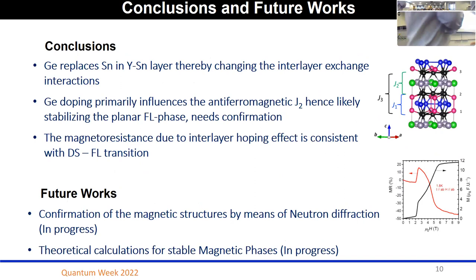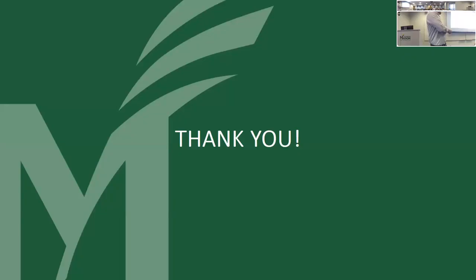So another reason to believe is by comparison of the magnetoresistance. So if we look at this point where there is a big jump in magnetization, there is very negligible change in magnetoresistance. If we look at the doped compound in the magnetization where there is big jump, we see an increase in magnetoresistance here. So this increase seen here is similar to the rise in magnetoresistance seen here. So from these two comparisons, we can see that germanium doping tunes the magnetism of the parent compound, yttrium manganese tin 6. And it looks like the fan-like phase is stabilized after this transition, but we are still studying this. So here are my conclusions. And we already have done neutron diffraction experiment for this sample. And we are analyzing our data. And Dr. Marlin has been doing critical calculations for us. Thank you.